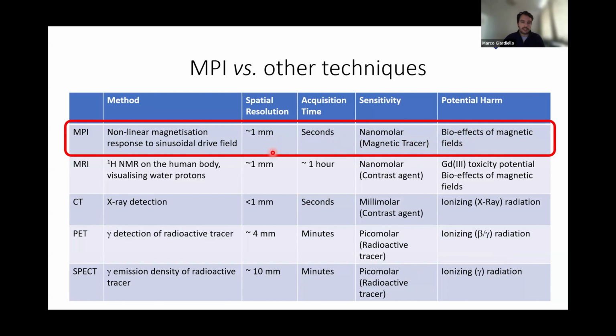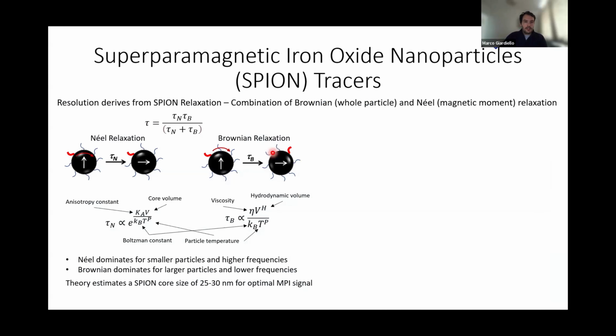There's a lot of work going on to try and make clinical strength MPI. So focusing on the SPION to begin with, superparamagnetic iron oxide nanoparticle SPION tracers. The resolution and your image intensity derive from a combination of the Brownian and Néel response in the presence of that sinusoidal field. So it's a combination of the two. That's your total relaxation.